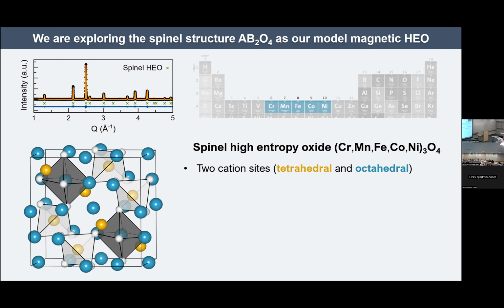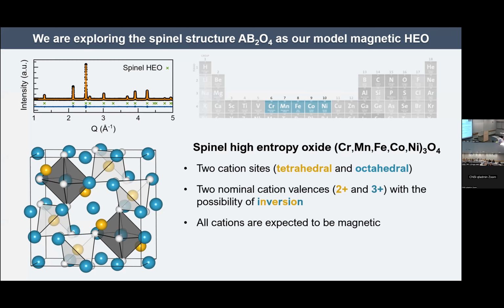Third, and this was actually the main design criteria, we wanted an entirely magnetic high entropy oxide. So at the point where we made this material, there were no completely magnetic high entropy materials. And we were eager to study how the disorder of a high entropy material would interplay with its magnetic state. And if we wanted to make a 100% magnetic material, there was really no better place to look than this particular part of the 3D block. You would have to really make a special effort in an insulating oxide to make any of these 3D transition metals non-magnetic. Yes, Sam? Well, in some sense, you have actually 10 different elements. That's right.